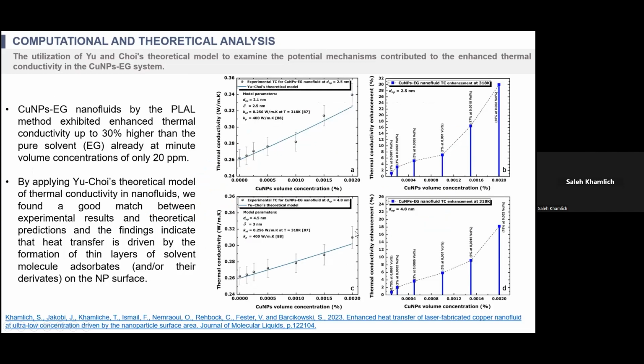So now these are the experimental results from our nanofluid, and this is the model that I showed you. It shows clearly that this material, which was made by the 515 nanometer wavelength, shows higher thermal conductivity and also enhanced heat transfer of around 30%. The other one, which we made using 1064, gives, of course, a model that fits the experiment very well, but again, when using 1064 nanometers, we have only 18% enhancement, which means that using a wavelength of 515 gives smaller nanoparticles and higher enhancement.